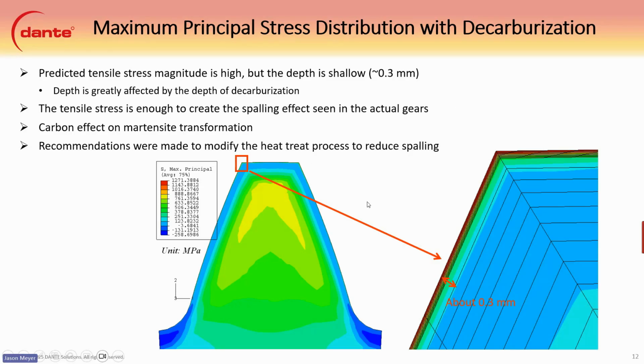The carbon effect on the martensite transformation, I talked about that again, but I'll reinforce that a little bit, how the surface transforms first here, given the higher MS from the lower carbon at the surface. And then once this region transforms, it pulls that into tension. So given the model here, we were able to see the issue, and recommendations were made to modify the heat treatment process to reduce the spalling.